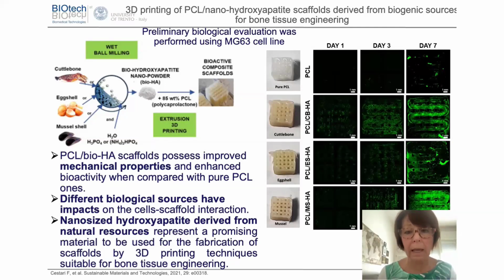These were an osteoblast cell line cultured up to 7 days. As you can see by looking at the green in the picture, you can see the difference between the pure synthetic polymer and the synthetic polymer in combination with the bioceramic. We did something like this by comparing with the commercial hydroxyapatite, and the results were very similar. The use of bioceramic is much more bioactive for bone cells because of the presence of microelements that nature combines in the shell of the mussels that are very beneficial for the metabolism of the bone cells.